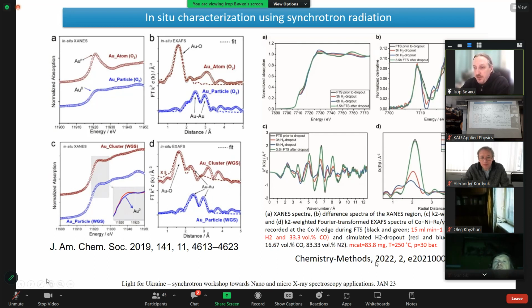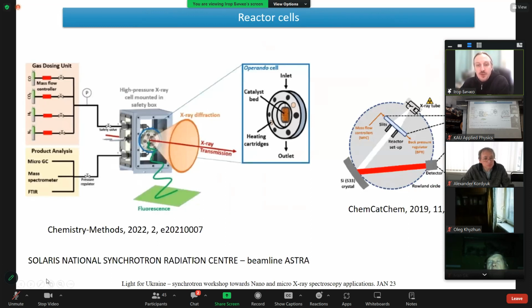And here I draw your attention to the conditions. This spectrum was recorded under conditions where the temperature of the sample was about 250 degrees C, and the pressure in the reaction cell was about 30 bars. Such experiments and such a setup are typical for a lot of synchrotron facilities. And for example, if we talk about Solaris, as I mentioned, the beamline Astra can provide this type of experiments.